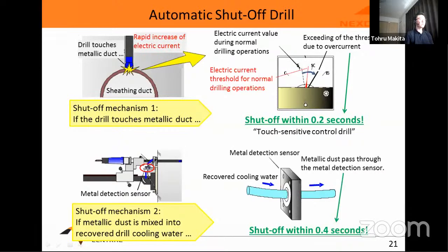There are two shut-off mechanisms. If the drill touches metallic elements, the electric current of the electric motor driving the drill rapidly increases, and when the electric current exceeds the threshold value, the drill stops. Another shut-off mechanism is functioned by a metal detection sensor installed on the cooling water tube. If metallic dust is mixed into the recovered drill cooling water, the metal detection sensor reacts to the metallic dust and the drill stops.